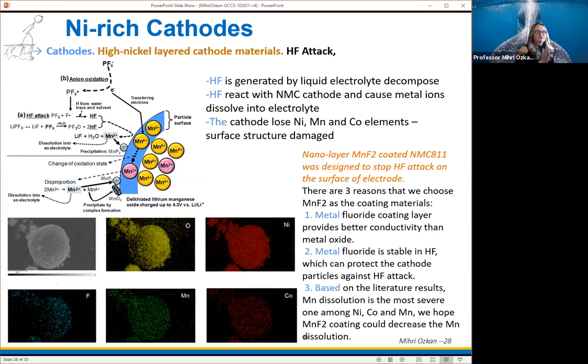We try to develop some prevention coatings, a nano layer of, in this case, manganese fluoride, is one of the films that we coated. It shows that the manganese fluoride is there, and we used standard NMC, nickel, manganese, cobalt type cathodes. It shows a very nicely, uniformly covered surface, and then we are doing both fast charging and standard charging just to see how stable these coatings are.